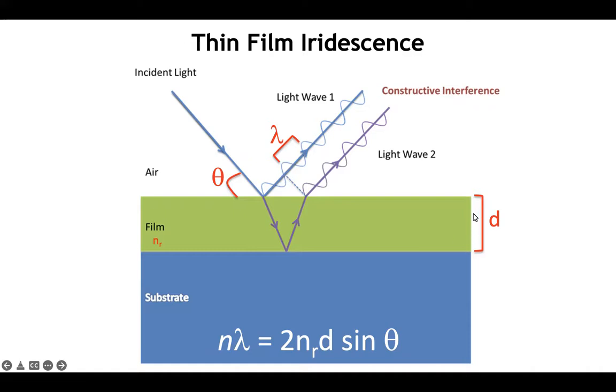A third is just the thickness of the film. And then finally, we have to take into account the refractive index of the film. So one can put it together using some high school trigonometry and demonstrate that this product here, 2 times the refractive index times the thickness of the film times the sine of the reflection angle, in order to achieve total constructive interference, all of that has to equal some integral multiple of the wavelength.